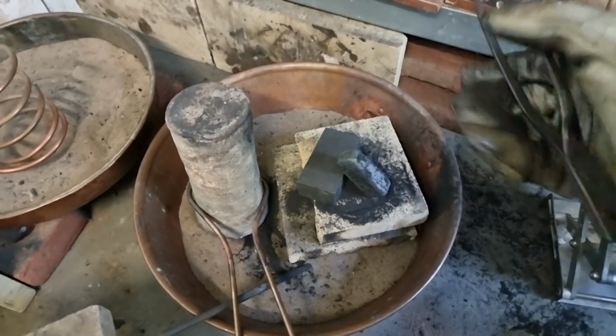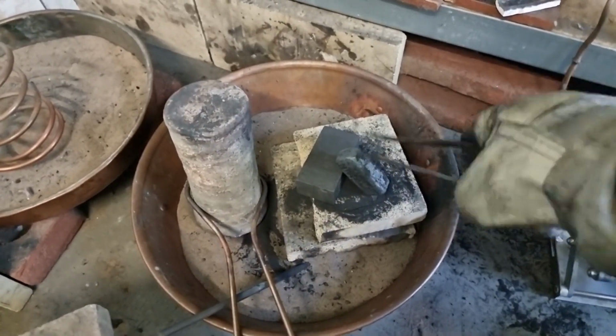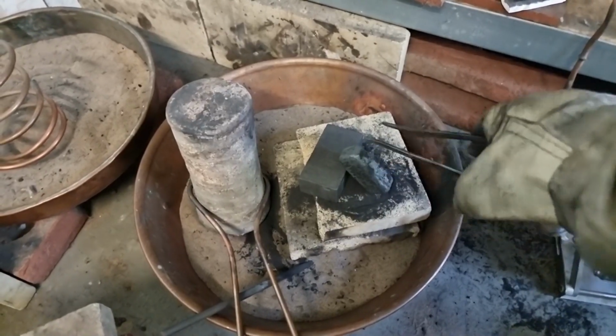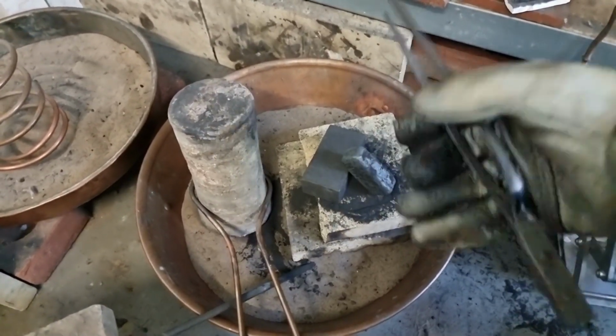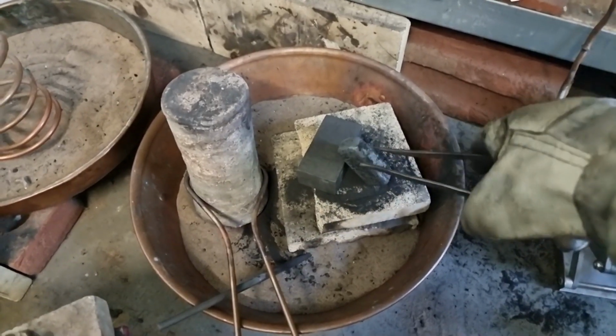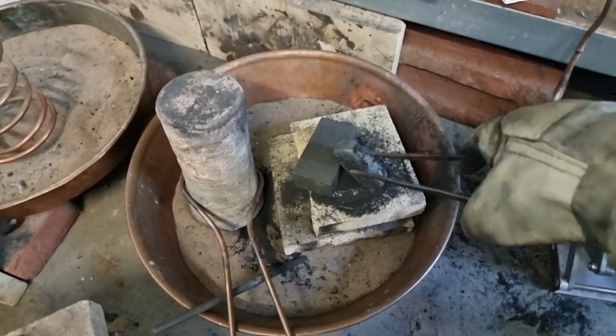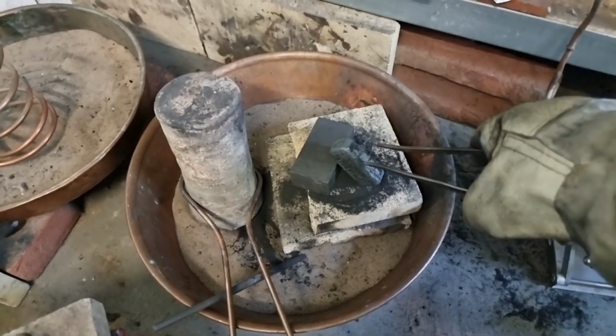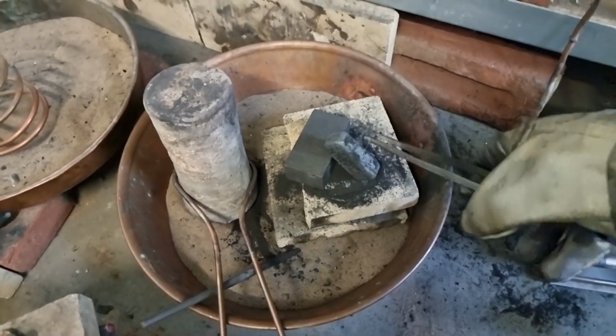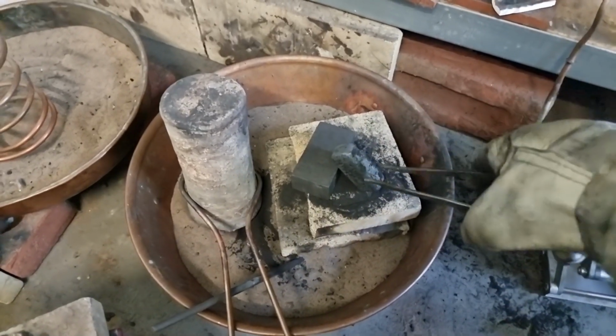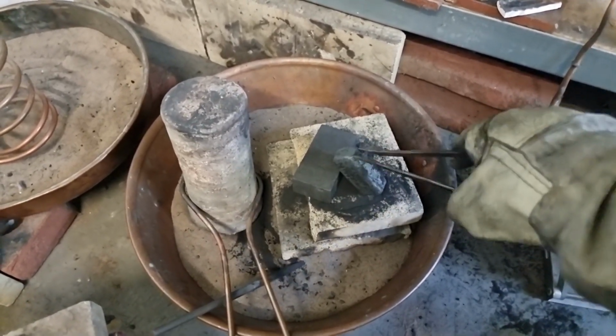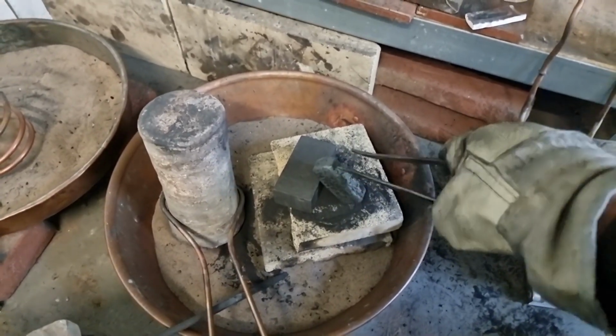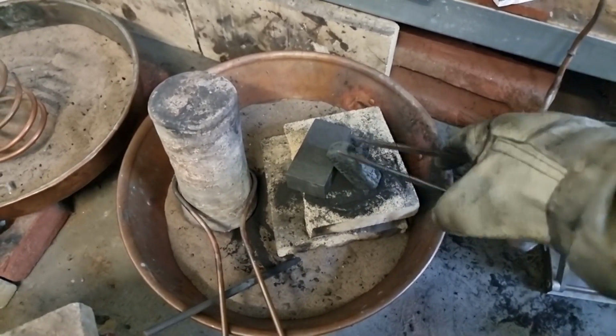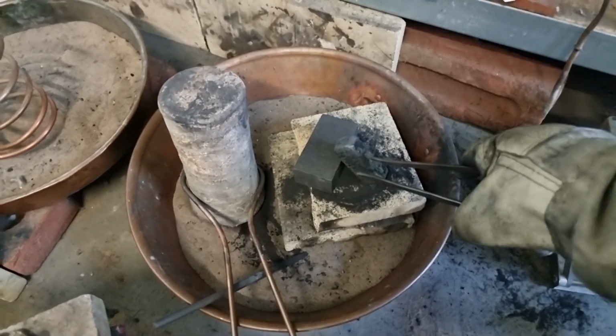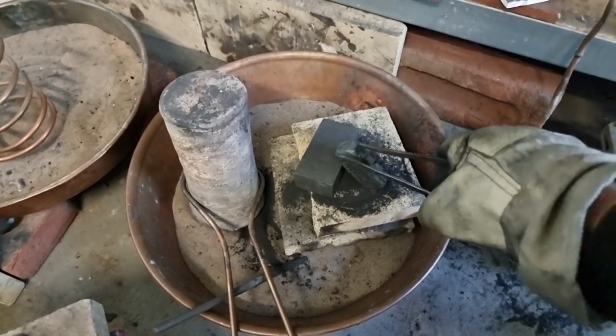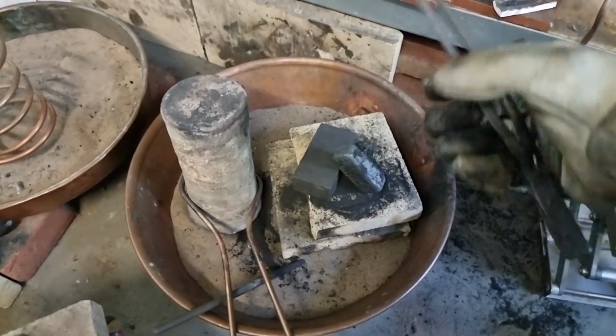So what they did, for example, they cast knives out of bronze, or even swords not of bronze but from cast iron, which of course were too brittle for practical use. But then they put those sword blades in a big furnace and heated that up for several days in a slightly oxidizing atmosphere, and by that they burned the carbon out of the iron by a diffusion process. Carbon gets constantly burned off from the surface, and then the carbon atoms slowly wander through the metal to the surface, where they get converted to carbon dioxide or whatever.